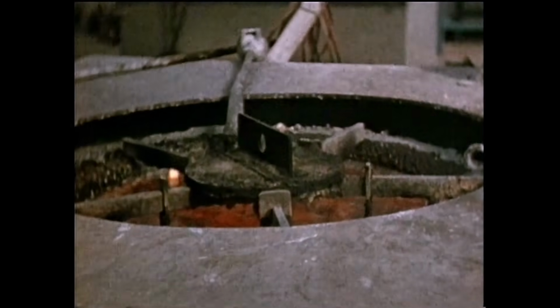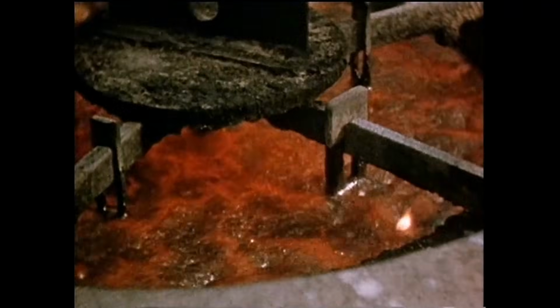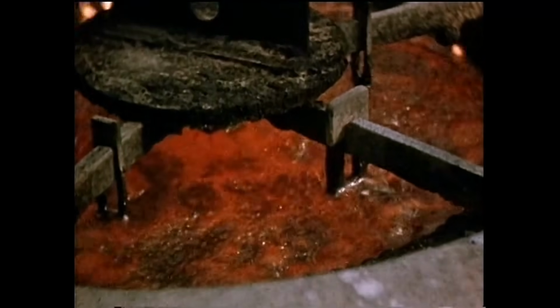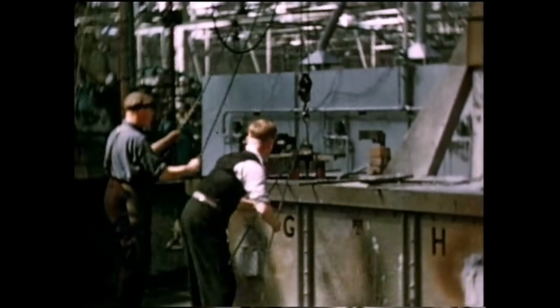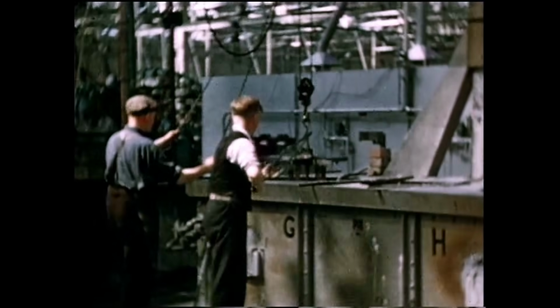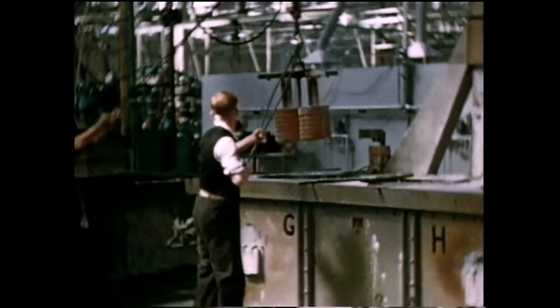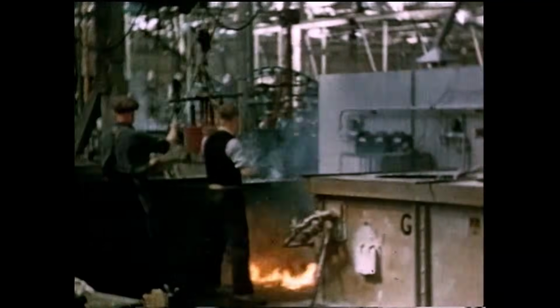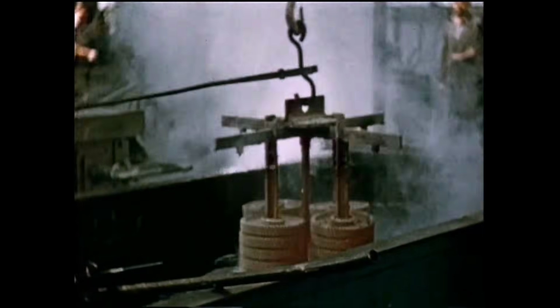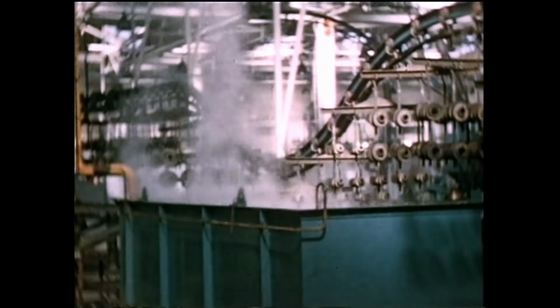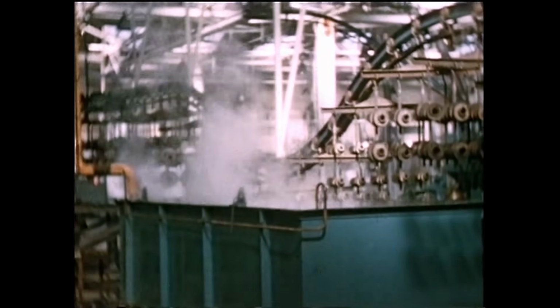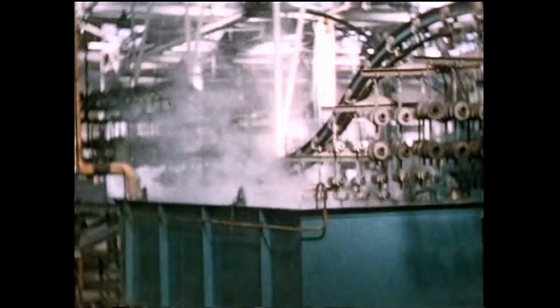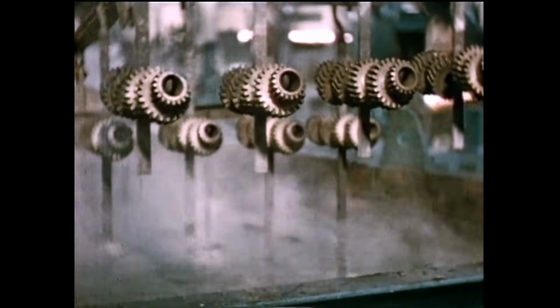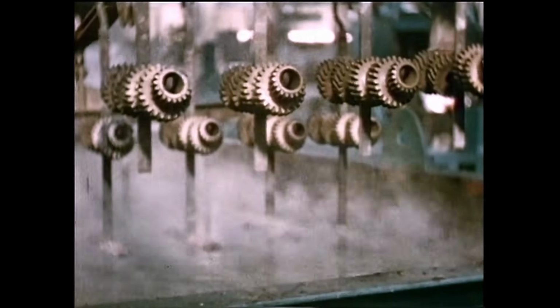Each machine shop is self-contained and has its own heat treatment plant. In the gear section, 8 cyanide furnaces deal with 2 tons of parts in 1 hour. The gears are hardened at 800 degrees centigrade and cooled by quenching in oil. They are now thoroughly cleansed by passing through 2 hot water baths and finally tempered for half an hour at 200 degrees centigrade.